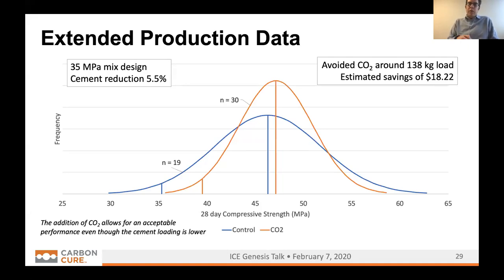What that means for them is that when you take out the cement, if you look at the Portland Cement Association's environmental product declaration for the carbon impact of cement produced in the United States, they say cradle to gate, there's 1.04 units of CO2 emitted for every unit of cement that's produced. So this producer, for each load of concrete, ends up saving or avoiding about 138 kilograms of CO2. And this is because the cement they didn't use has a CO2 impact.